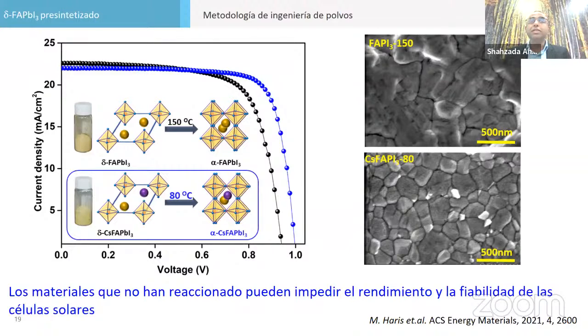And the good thing is that if we have the pre-synthesized perovskite, there will be no unreacted lead, because in the normal route, we take lead iodide and methyl ammonium iodide and react them. So some of the lead iodide is unreacted. In this way, there is no unreacted lead iodide, and this is a good approach we are adopting. Most of the community is also adopting it. At 80 degrees they convert to very good crystals. At 150, they even go to large crystals.